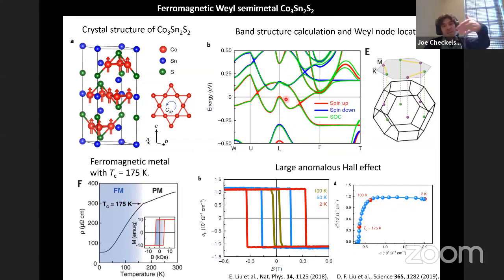And in terms of electronic structure, these are just calculations. I'll show you the data in a moment. What was predicted was that you should get these kinds of Weyl points sitting in k-space. And these Weyl points, among other things, can contribute to the transverse conductivity in a way that is related to what you see for quantum Hall physics in 2D, but it's sort of a 3D analog of that. And for example, you do see a large anomalous Hall effect in these systems that arises one way or another from these Weyl points.